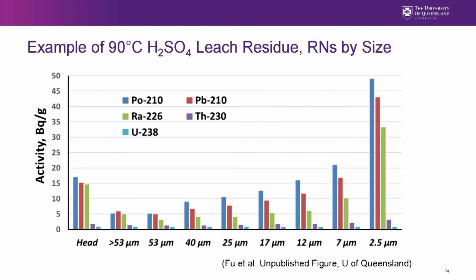We took a look at the size-by-size distribution of the leach residue at these conditions. I'm not sure if it's exactly the same sample shown in the previous table, but this is an example of how the radionuclides are distributed on the different size fractions, and it's very clear that they are going on surfaces, and the 2.5 micron, the smallest size fraction here, has a very high RN load compared to the average materials here.